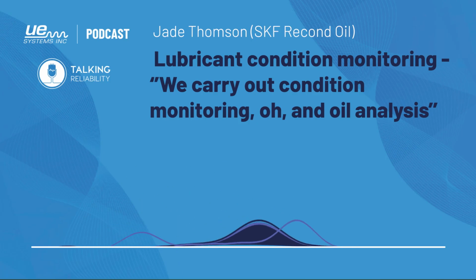And then we look at wear, so all the tests that give us an idea of any wear occurring. And again, we don't just want to see there's 50 ppm of iron in there, it was 40 last time. We need to look at why is that wear occurring, merge it with the contamination results, and look at ratios to other wear elements, but we'll go through these with case studies in detail a bit later on.